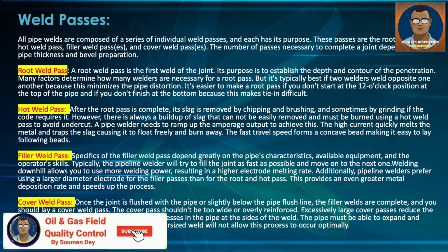Hot pass weld. After the root pass is complete, its slag is removed by chipping and brushing, and sometimes grinding if the code requires it. There is always a buildup of slag that cannot be easily removed and must be burnt using a hot weld pass to avoid undercut. A pipe welder needs to ramp up the amperage output to achieve this. The high current quickly melts the metal and traps the slag, causing it to float freely and burn away. The fast travel speed forms a concave bead, making it easy to lay following beads.